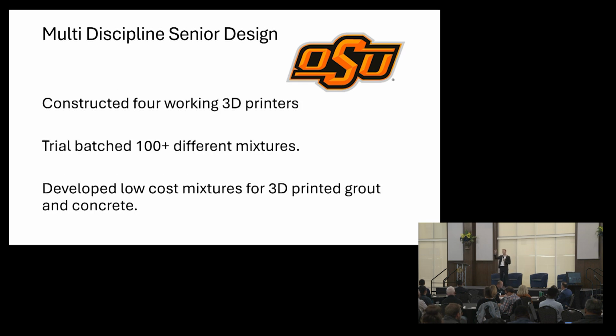We built 4 working 3D printers. Now, 3 of them didn't work very well, but baby, you only need 1. You only got to have 1. That's what's important. We trial batched more than 100 different concrete mixtures, okay? We did grout mixtures, and then we did concrete, real concrete that has aggregate inside of it, all right?